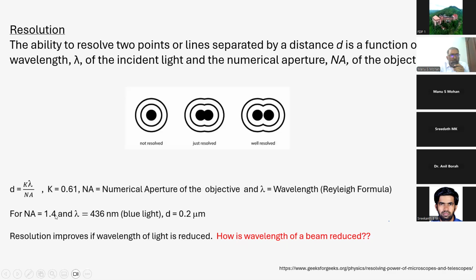So the numerical aperture is a product of sin alpha and the refractive index - that is 1.4. For glass the refractive index is 1.5, and alpha, sin alpha is 70 degrees. If you multiply, you get 1.4, and then if you substitute, you get 0.2 micron. So that is the limiting thing in an optical microscope, apart from depth of focus, magnification.